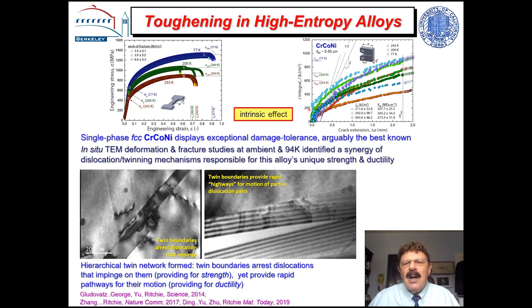These are called R curves, JR curves in fact, and the toughness of these materials at liquid nitrogen temperatures is almost 300 megapascal root meters. Now, typical aluminum alloy would be 30 megapascal root meters. Silicon is 1 megapascal root meter, so these are really tough materials, and in fact, their crack growth toughness is as high as 450 megapascal root meters, which is a mind-boggling number.